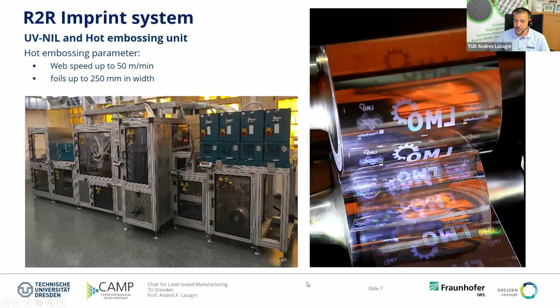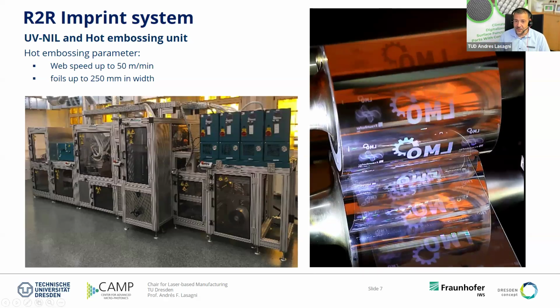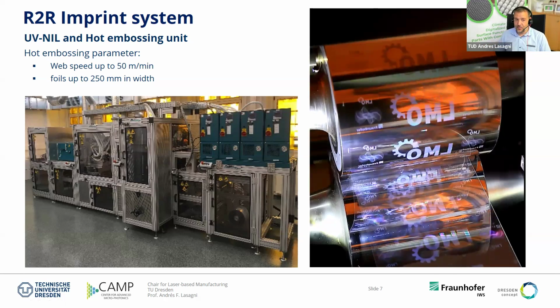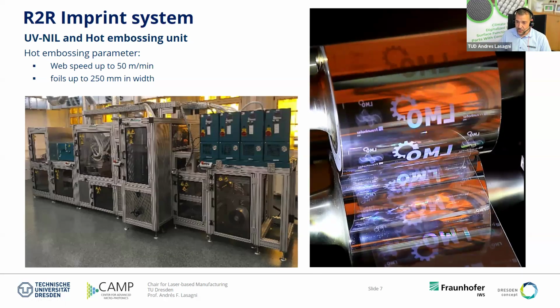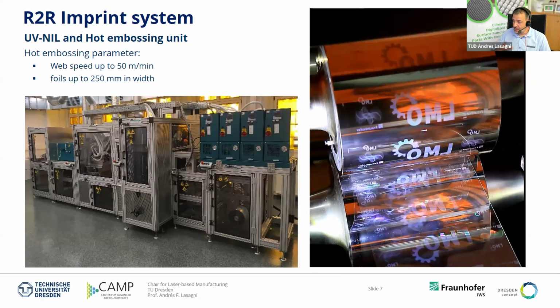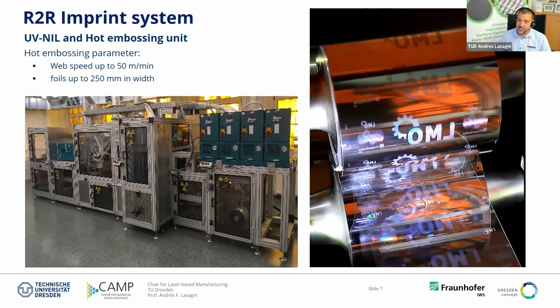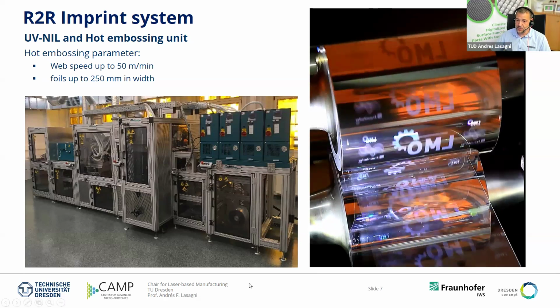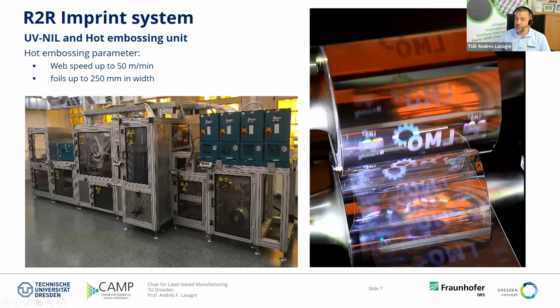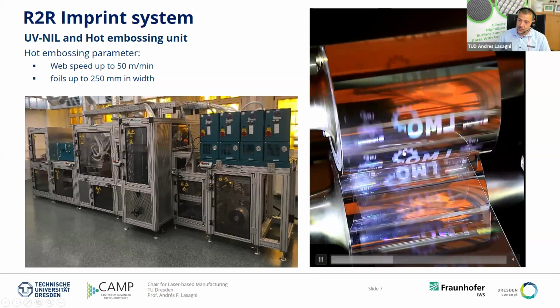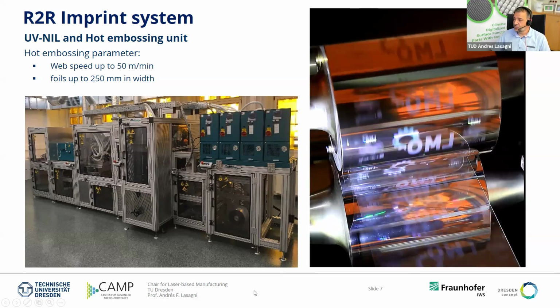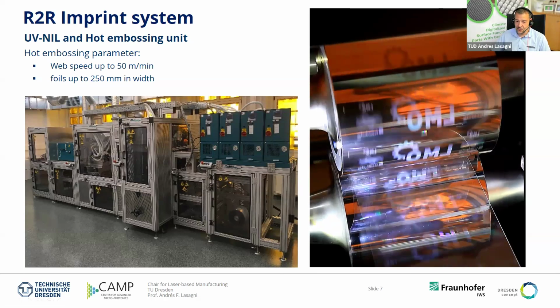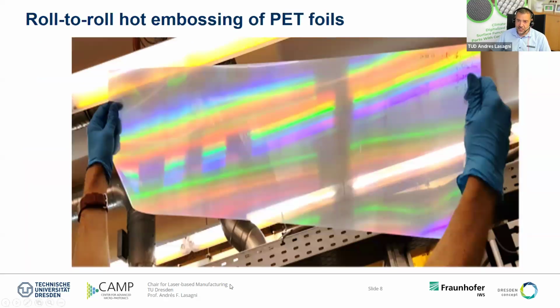They are very small, so light starts to be diffracted. And then we can put, for example, such cylinders in roll-to-roll equipment. And so we can also make different kinds of motifs and so on. Then we just need to apply temperature and pressure between these two cylinders that you see here. And then you see how the polymer foil is getting the structure from our texture sleeves. And one example here of a large area treated polymer, you can see there. So this is for applications, for instance, for antibacterial properties.